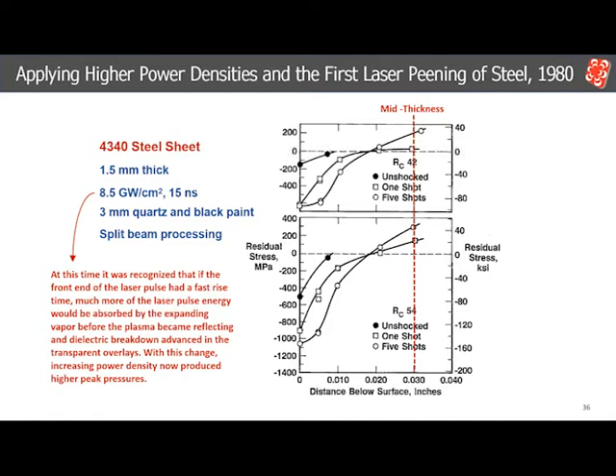It was about this time that we realized that if the front end of the Gaussian pulse was cut off to create a fast rise time in front of the laser pulse, we could reach higher peak pressures by increasing the power density. By sharpening the leading edge of the laser pulse, most of the beam energy would be quickly absorbed by the expanding vapor before the plasma progressed to reflecting too much of the beam and dielectric breakdown of the transparent overlays progressed too far. Subsequently, power densities above 5 gigawatts per centimeter squared are now routinely used.